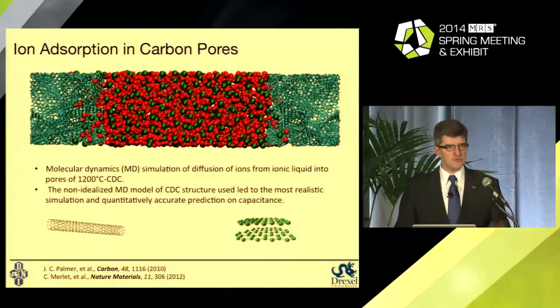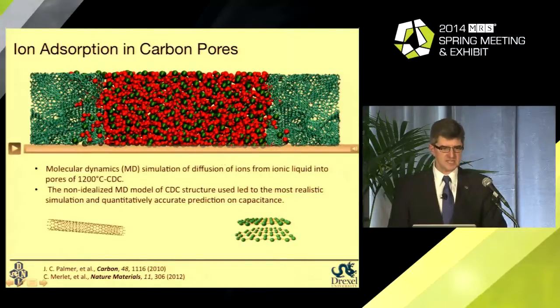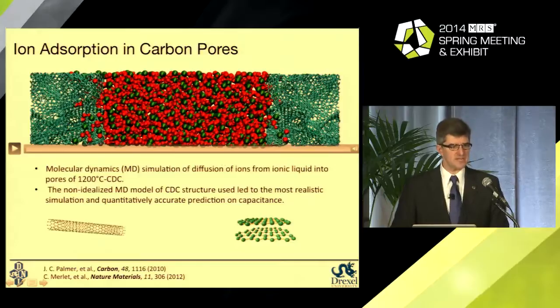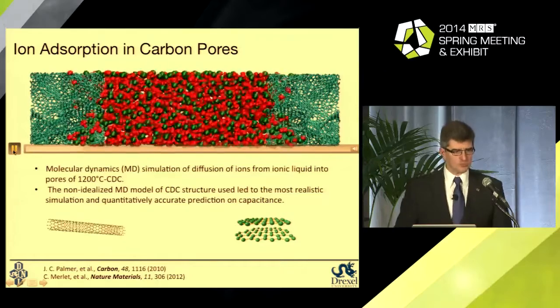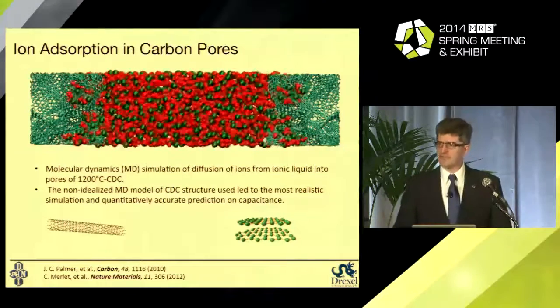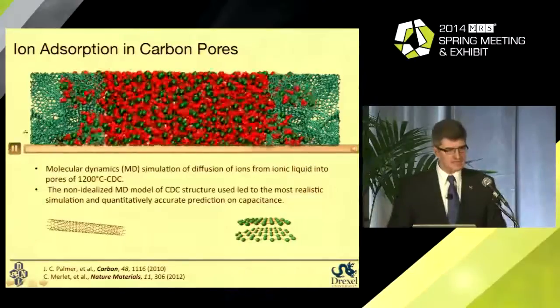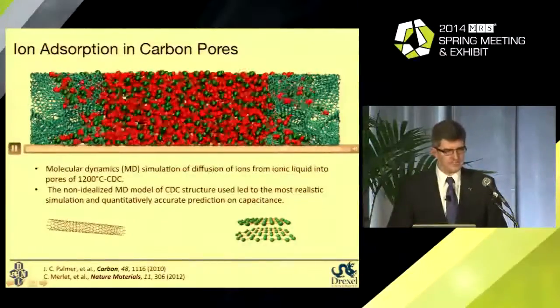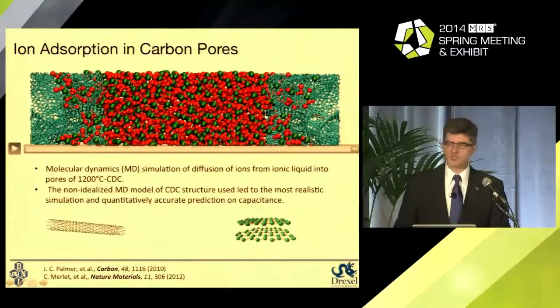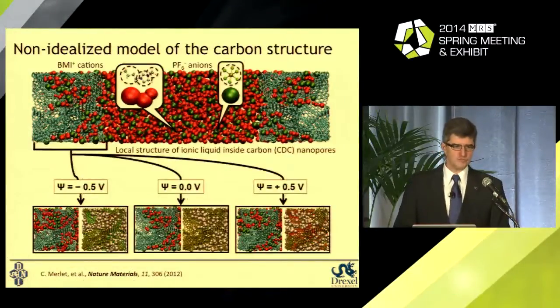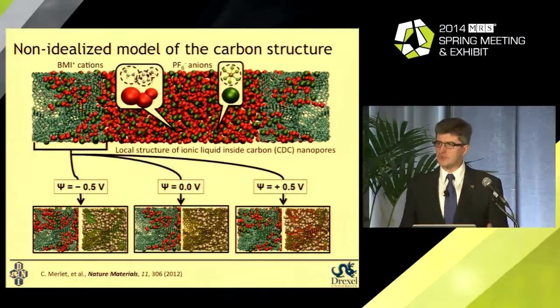However, I showed you before the structure of real carbon, or you take activated carbons here. They don't have slit pores, clearly shown here. They don't have cylindric pores. They're three-dimensional networks here. And working with Keith Gubbins' group, we were able to produce models of carbide-derived and activated carbon. And Mathieu Salanne at University of Paris 7 did molecular dynamics simulation showing that actually ions will go into pores of this material. Moreover, in case of, say, ionic liquids, negative ions will drag positive ions along and vice versa. So there are always counter ions penetrating into these pores here.